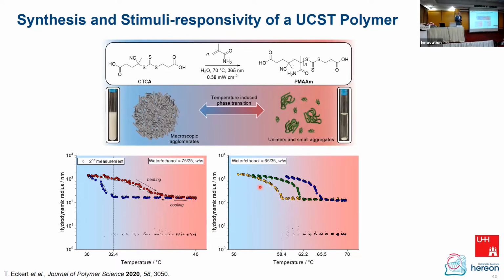Why is that? Because our homopolymer becomes a random copolymer by hydrolysis of the amide group. It becomes carboxylic acid. Then a polymethacrylic acid doesn't have a UCST, at least not that we can measure. And so the whole thing becomes more and more soluble. That is a pity, of course, because we don't have a really nice reversible behavior, reversible in the sense that our material is not destroyed. Here it is gradually destroyed.